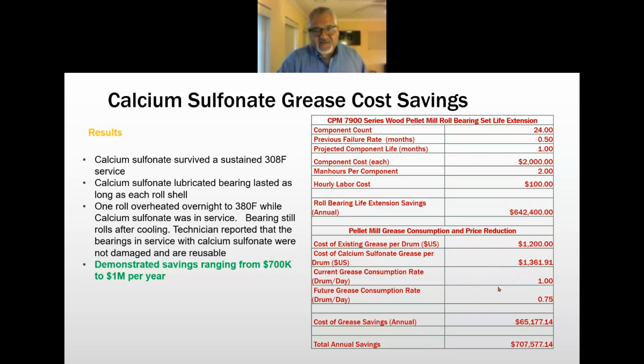They're feeding these 12 pellet mills with a drum, so we're just using drums as a rate unit, drums per day. They're using about a drum a day. We could reduce their consumption rate to 0.75 drums per day. Our grease costs more. It's like $1,361.91 per drum.